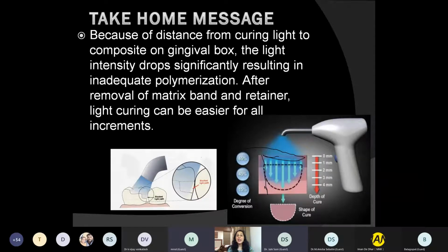And this is what I said, that in most of the cases when you're doing a class 2, I believe the gingival seat is at least 4 millimeters down from the surface. And imagine the degree of conversion on the surface is 65%, the monomer being changed into polymer, and at the 4 millimeters level, it is only 15%. So this is wishful thinking, that we are thinking that the gingival seat material is polymerizing, but actually it is not. And when it does not polymerize, only 15% degree of conversion takes place.